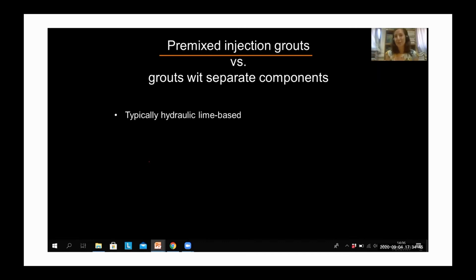Of course, if you have a different binder in terms of original materials, that's a different story. But talking about lime-based plasters, these may be used. So why hydraulic lime? Because the delamination is behind, basically the paint layer is behind the plaster or in between the plaster and the support. And therefore the CO2 access is limited. So it's not in direct contact with the air very often, and therefore carbonation may actually be very slow or difficult to occur.